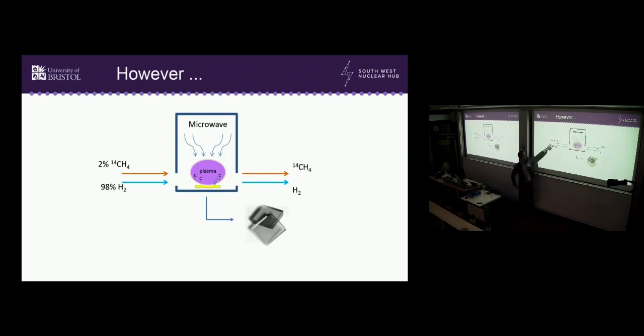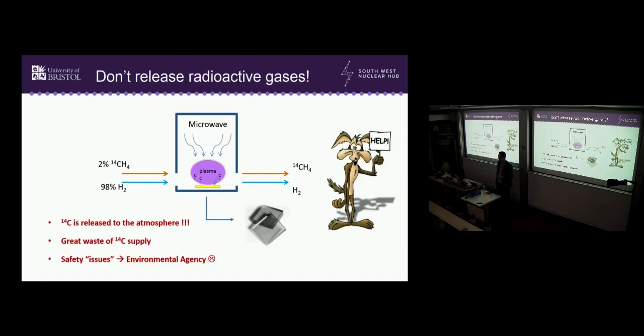So normally you have your 2% methane and you have your hydrogen carrier gas. And if this was normal diamond growth, then you're about 1% effective in terms of converting the methane into diamond. Most of your gas goes straight out the back of the machine, up the chimney, and out into the environment. And of course, if you're using carbon-14 methane, well, I think you can imagine. You release a radioactive gas to the atmosphere in large quantities, okay? You're wasting your carbon-14. And of course, the Environment Agency then gets very cross, and I think the initial fine would be 2 million spot fine, and probably I lose my job as a professor at the University of Bristol and maybe even go to prison, who knows. So if you want to grow a radioactive diamond, you can't do it the way that everyone else does. You have to do it differently.